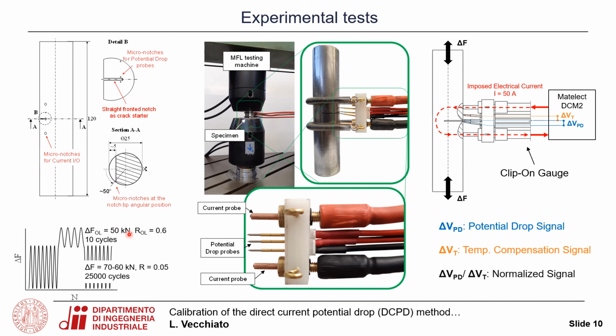The potential drop values were measured thanks to a clip-on gauge-like device designed and realized for the purpose of these tests, in order to both inject the current and measure the potential drop as close as possible to the crack tip, according to the most sensitive configuration we have seen before. The output of this device and of the DCPD device was the main potential drop signal and a reference one, which is normally used for temperature compensation. The temperature compensation is performed by simply evaluating the ratio between these two signals, so the blue and the orange one.